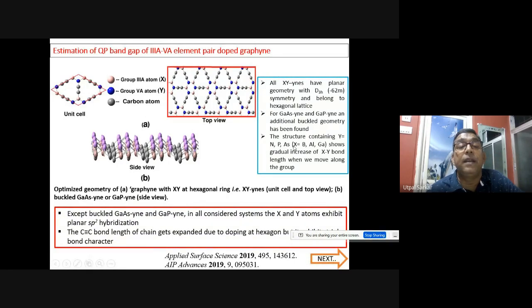So we have considered here boron, aluminium, and gallium. And for Y we have considered nitrogen, phosphorus, and arsenic. Okay, so all these XY-ynes have planar geometry with D3h symmetry and belong to this hexagonal lattice. Gallium arsenide and gallium phosphide, these two have some additional buckling. You see here, buckling structures, and the structures containing nitrogen, phosphorus, arsenic show some gradual increase of the bonds depending upon the ionic radius. Okay, so when I move along this group, whatever is expected from chemical intuition is reflected in our calculations also. Okay, except for the buckled structure for these two, all other systems exhibit planar structure like this. Okay, and it is sp2 hybridized.